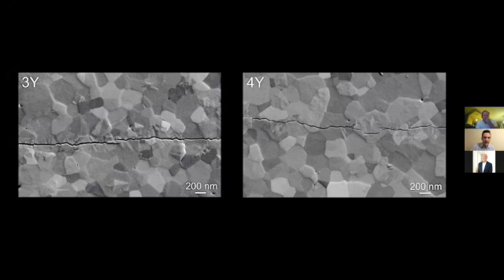And they did the study, and I'm simplifying what they did, but they got some 3Y zirconia, they start a crack in it. And once they start a crack, the zirconia will start to transform. And you can see, this is a different view of the grains of zirconia. The ones near the crack look kind of, I call them squiggly. And that's where they've transformed, and they've tried to do their magic and stop the crack from growing. But then they would push the crack a little further, and it would transform again and stop it. And then they push it further, and you could see they keep on transforming and transforming, and it's just doing magic, magic, magic, magic. I just think little fireworks of magic happening as they try to push this crack along through the 3Y zirconia.